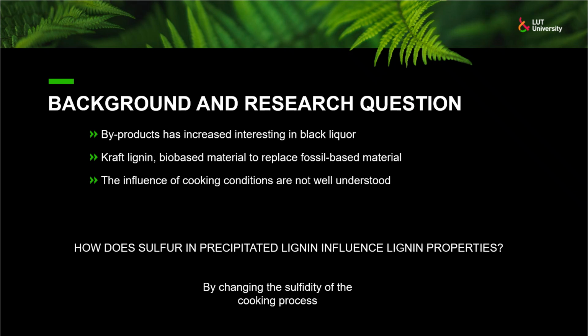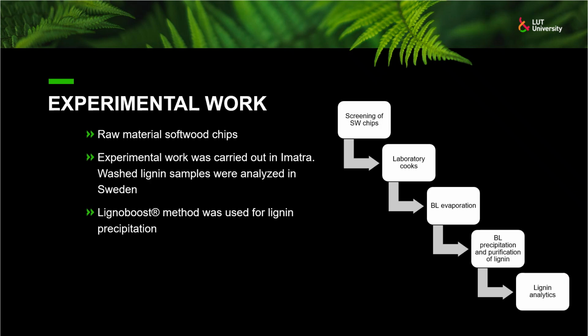The research question was investigated by varying the sulfidity of the white liquor across the trial points. The experimental part consists of 5 main stages: chip screening, laboratory cooks, evaporation of black liquors, precipitation of black liquor and purification of lignin with the LignoBoost method, and lignin analysis. Most of the experimental work was carried out at Imatra Research Center, while the lignin analyses were done in Sweden.